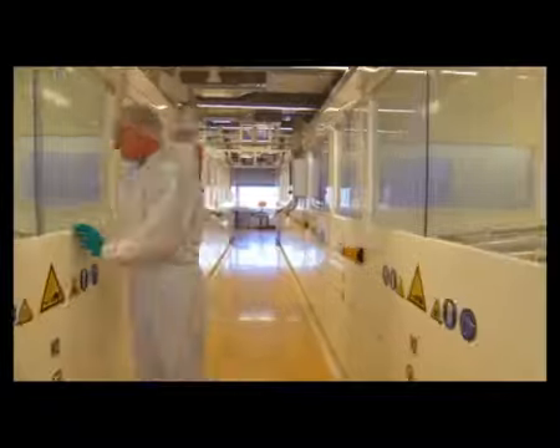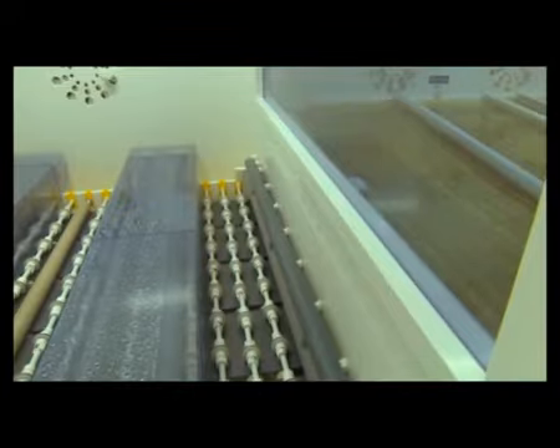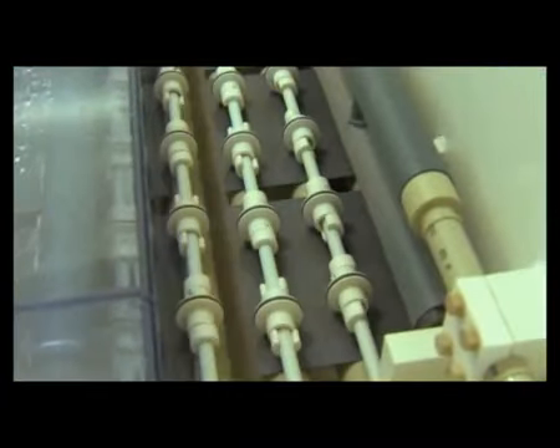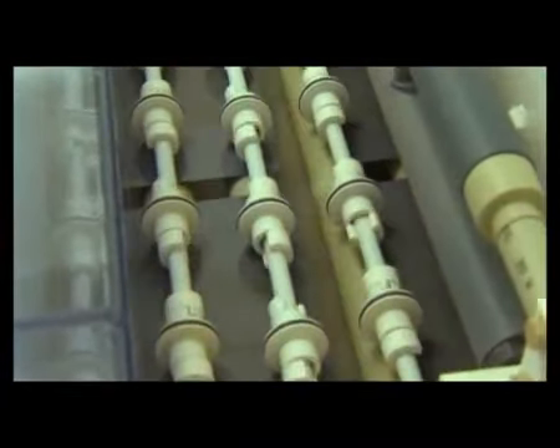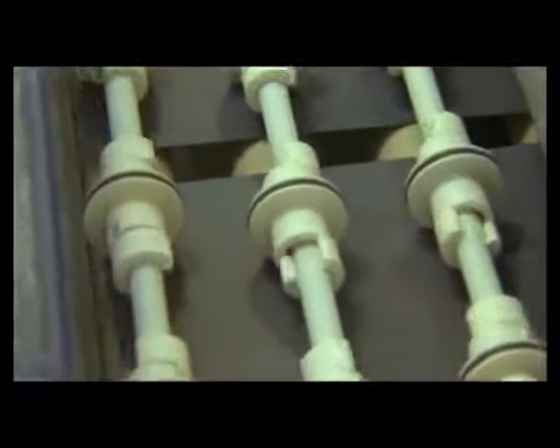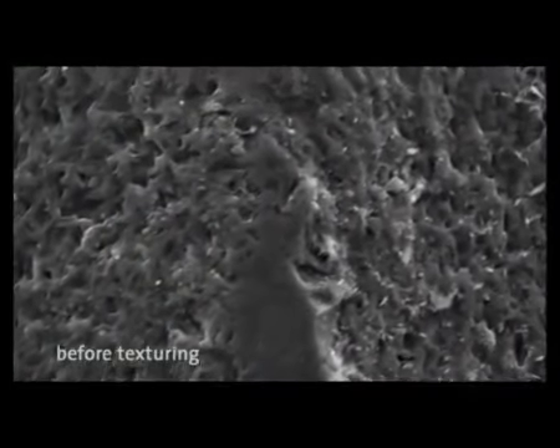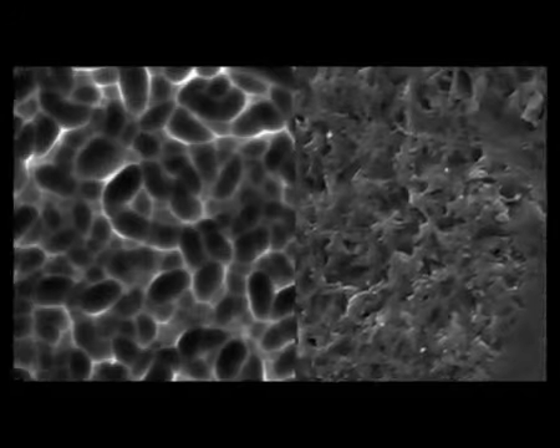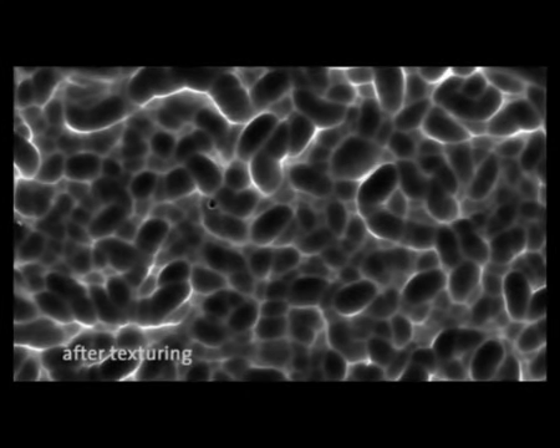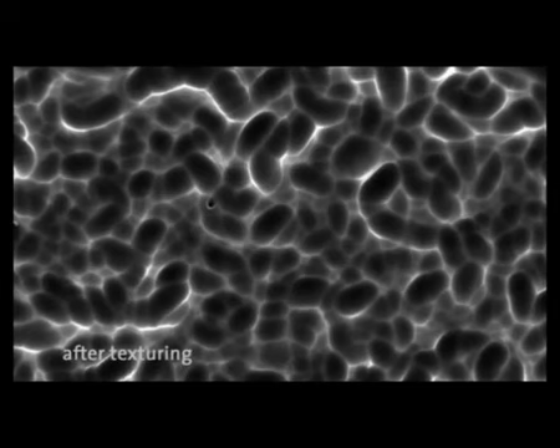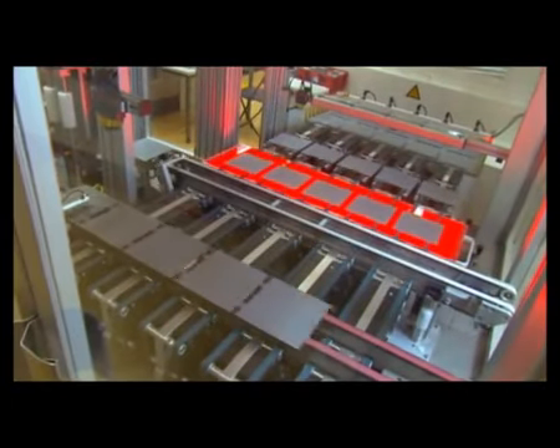Under clean room conditions, the wafers pass through additional cleaning baths, where every last bit of silicon sawdust or kerf that accumulated during the wire saw process is removed. These baths also contain a variety of chemicals that etch the surfaces of the wafers, a step that experts refer to as texturing. Zooming in on the wafer by a factor of 10,000, one can see how the surface structure changes. Countless dimple-like recesses become visible that give the future solar cells a larger surface area while minimizing unwanted light reflections. As a result, the cells can absorb more sunlight and generate more electric energy.